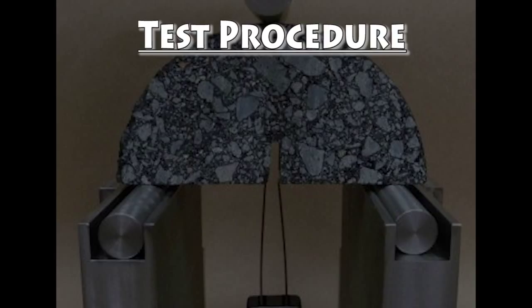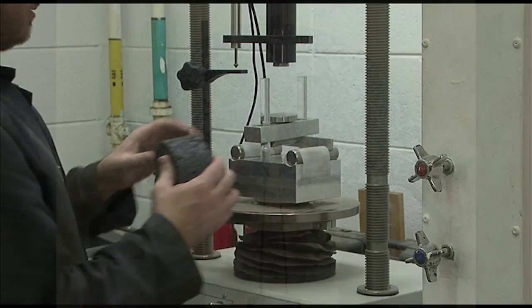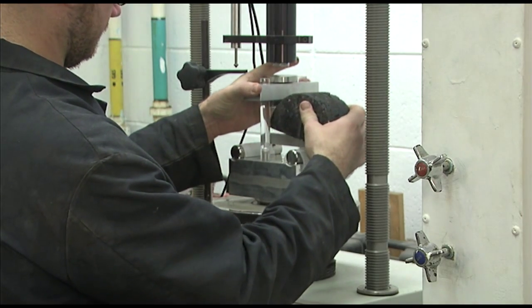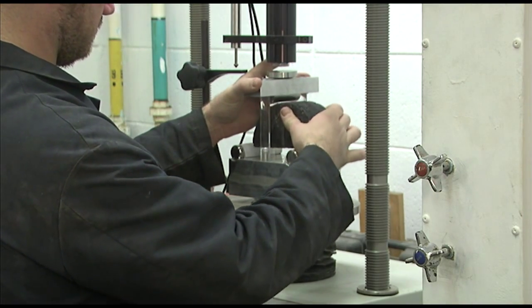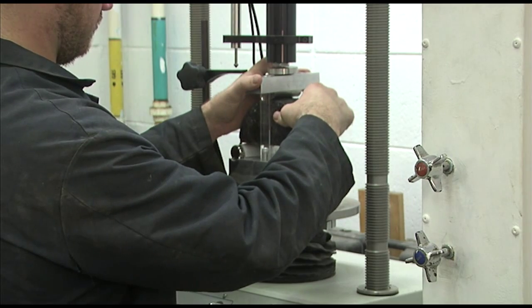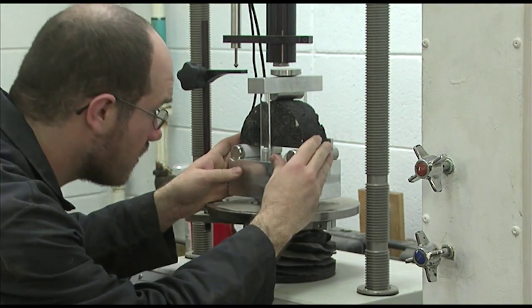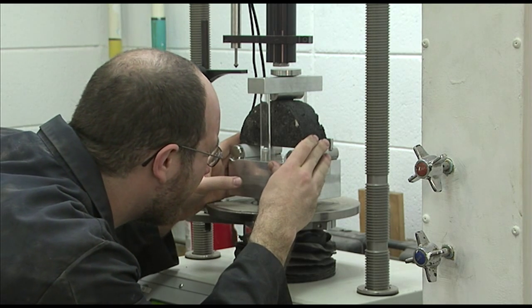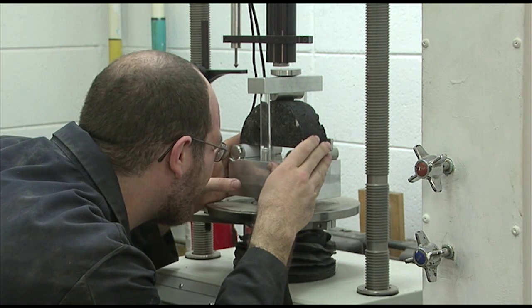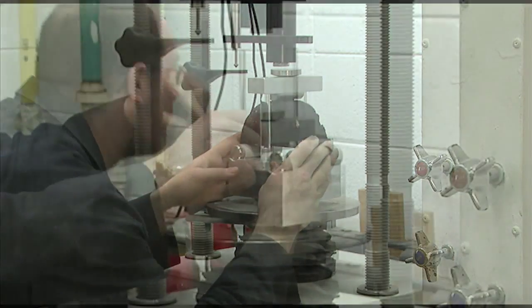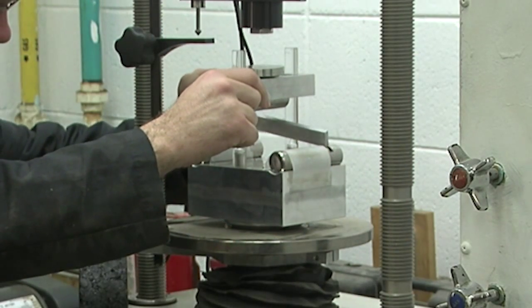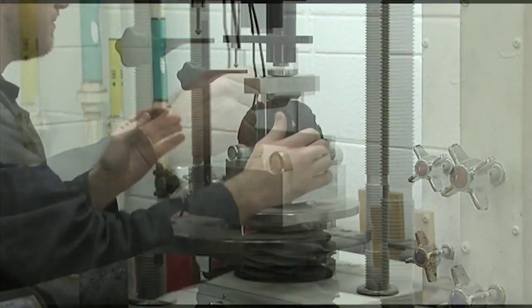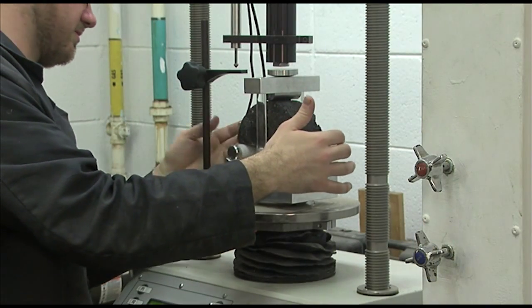The test procedure requires a minimum of 30 minutes of sample conditioning before testing can begin. The first step in setting up a specimen for testing is to set the specimen on the support rods. Remember to put your friction reducing membrane in between the specimen and the support rods to allow free movement. Verify that the specimen is level and centered in the loading frame. Some SCB loading frames come with a back plate to help with proper alignment. The back plate should be removed prior to testing.